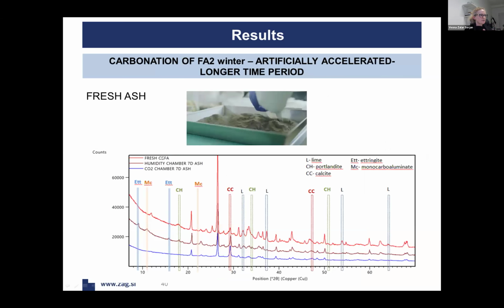So here is the comparison of fresh ash as it was collected, after humidity chamber, where it was kept 7 days, and CO₂ chamber where it was kept also 7 days. It can be clearly seen that in the case of the humidity chamber, some hydration products were formed, like ettringite. In original fresh ash, it was not present. Here it was. You can also detect the peaks from AFm phases, which also represent the hydration product. We can clearly see the increase in the peak of the calcium carbonate, so of the calcite, and the depletion of lime. Here, the peak is smaller than in the original one.